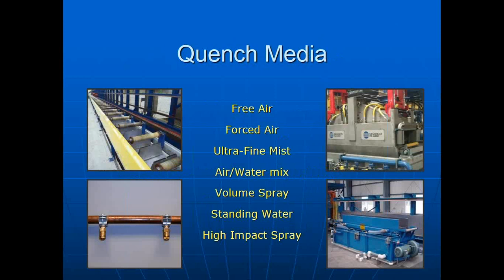It starts with free air. A 6063 alloy, that's what we sometimes call an architectural alloy, not a structural alloy. As we said before, if it meets your specifications, you can use it. For up to about a 3/16 inch wall thickness, it will meet T5 properties in free air. Just extrude it, leave it out on the table, it's going to make properties. As the walls get thicker, you may need to add some forced air cooling, but free air can get the job done for thin wall architectural alloys.